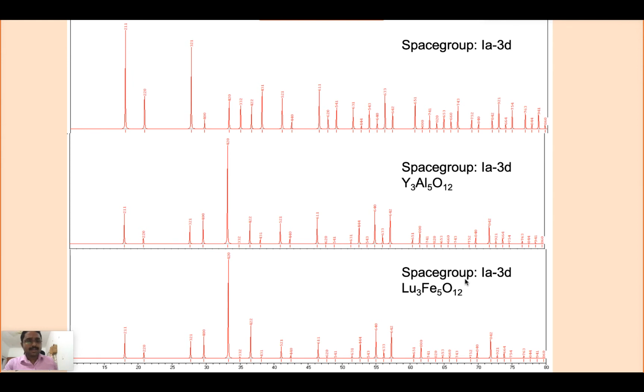Then what about the space group for Lu3, lutetium iron garnet? You can see the intensities are always different because the atoms are different. So you should be very careful with analyzing the sample. This is another example, an example for profile fitting. So all these peaks are correlated.